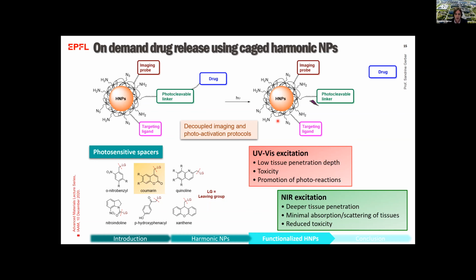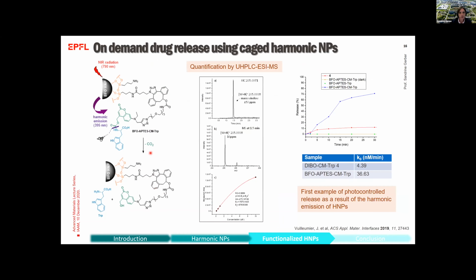So what we performed was to introduce a coumarin-based spacer between a molecular cargo and the surface of the nanoparticles, and then try to release the cargo using the harmonic emission of the nanoparticles. We ended up with the synthesis of this ligand, which contained the coumarin spacer. Here you have tryptophan as a model molecular cargo, and the spacer allowing the conjugation at the surface of the nanoparticles through this click reaction.